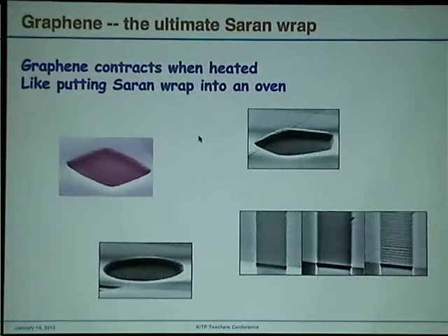You see these very nice periodic ripples form around this square, this hexagonal, and the circular hole. And you can also see that the ripples are all aligned perpendicular to the edge, depending on what your edge is. So this is basically the attempt of the membrane to release a strain from this thermal expansion.